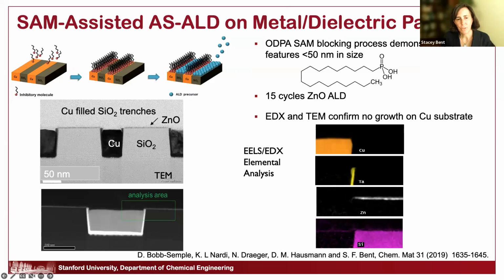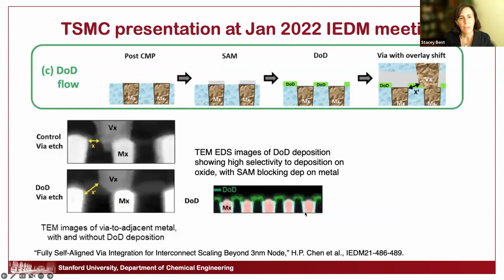So here are copper-filled trenches in SiO2, where we've first exposed it. Our first selective step is to expose it to this inhibitor. The second selective step is to do zinc oxide ALD, and you can see the zinc oxide goes down only on the SiO2, and you can see over here on the right in the elemental analysis, you only get zinc sitting on top of the silicon regions and not on top of the copper.